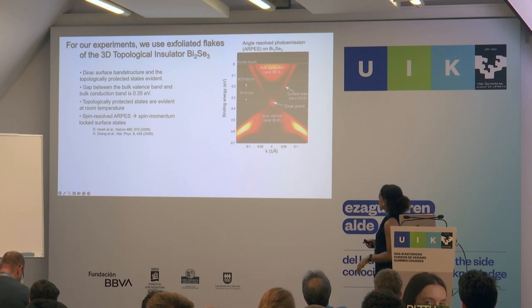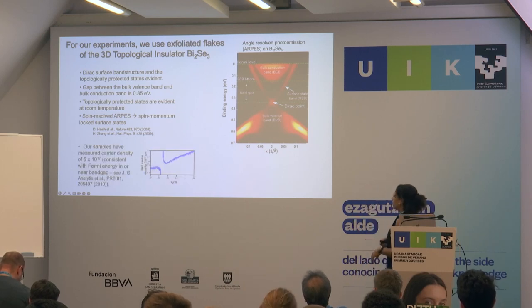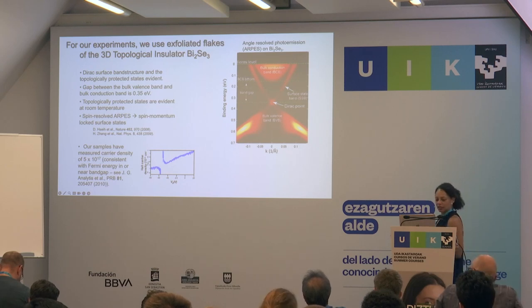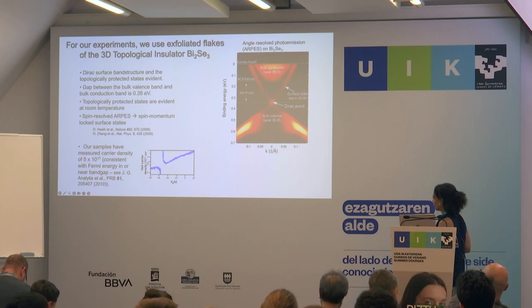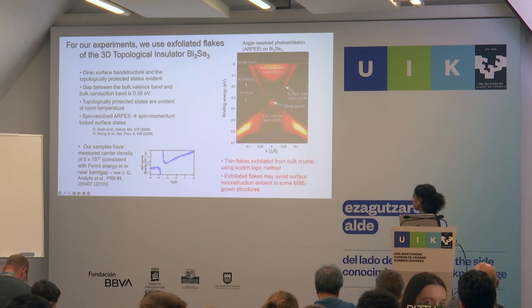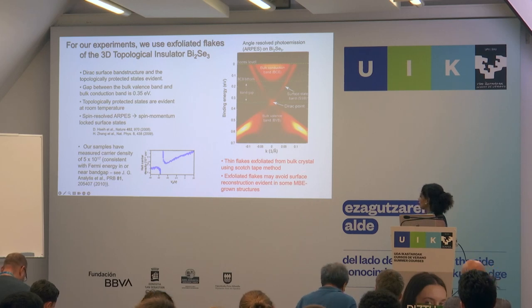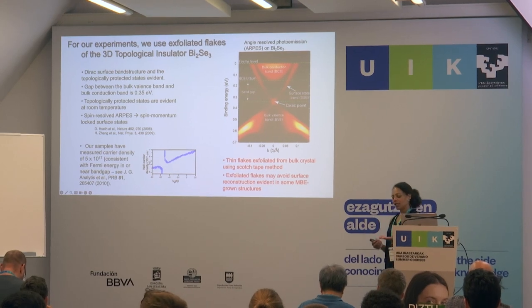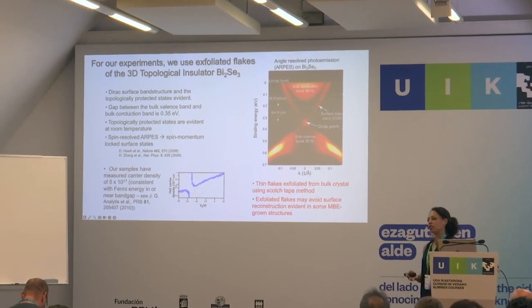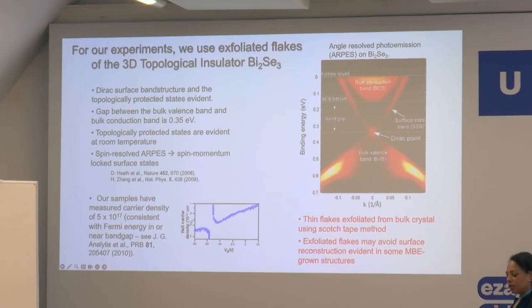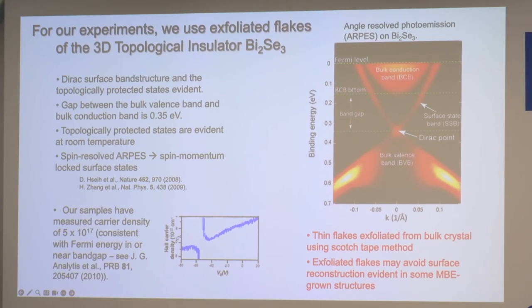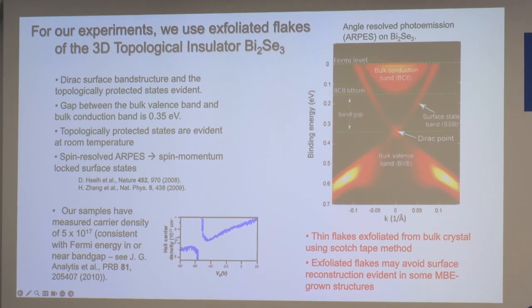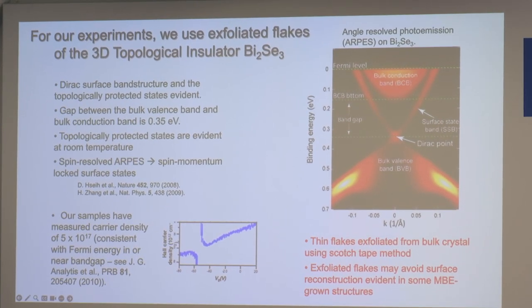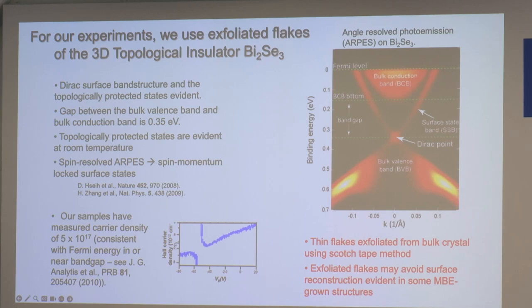Again, we use these 3D topological insulators. We believe that in these systems, based on our doping and other properties, our Fermi energy was close to the gap in this case. We again have thin flakes that are exfoliated from bulk crystals using the Scotch tape method. I mentioned here that the flakes are actually important because if you try to do these experiments on MBE-grown systems, in MBE, there's often a dead layer at the interface between one material and another. So if you have a ferromagnetic topological system, it's unclear exactly what's happening at the interface there.